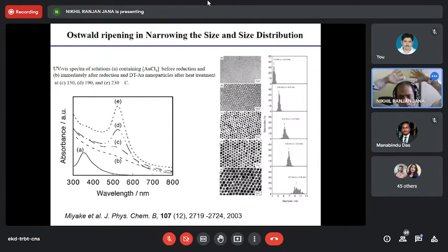I am not going through details. There are standard methods. You can make gold nanoparticles in an aqueous-organic interface and finally transfer them into the organic phase. So gold nanoparticles are dispersed in an organic phase, toluene, let's say, and you are heating it. This is called Ostwald ripening. You are heating it at a certain temperature and for a certain time.